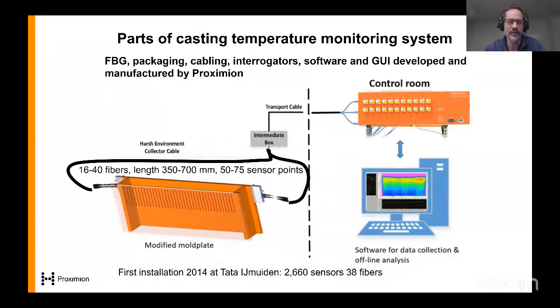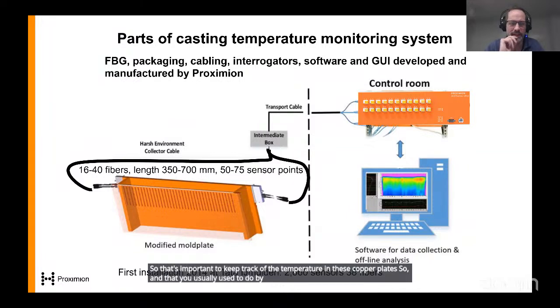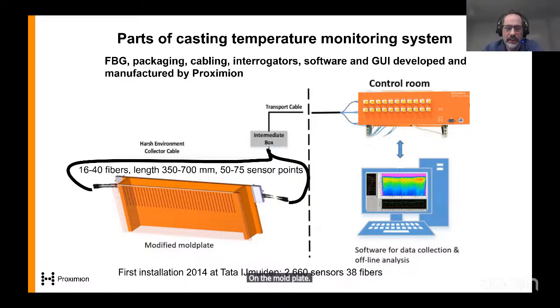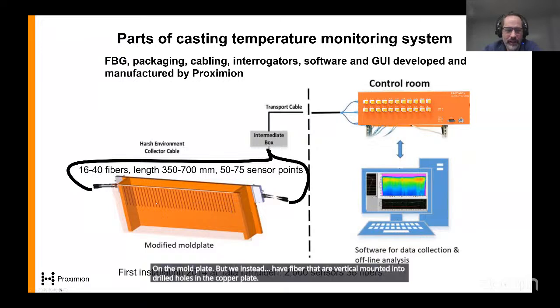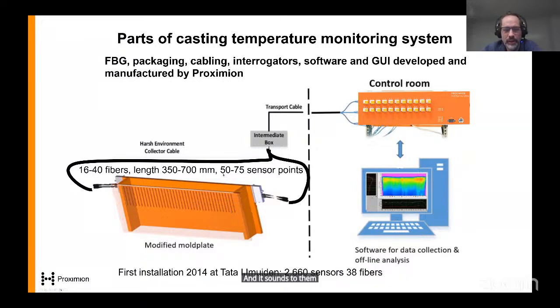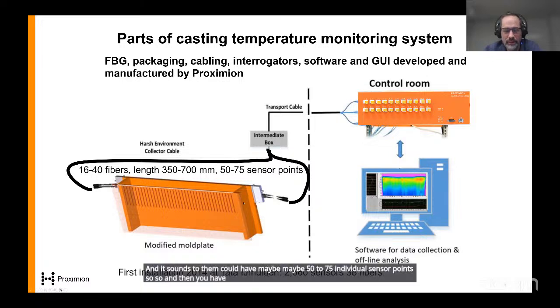That you usually do by thermocouples, but you can have only a very limited number of thermocouples, maybe 16 on the mold plate. But we instead have fibers that are vertical, mounted into drilled holes in the copper plate, and each sensor could have maybe 50 to 75 individual sensor points. And then you have this on all the plates in most cases. We also did the first installation in 2014, so this is quite mature now.